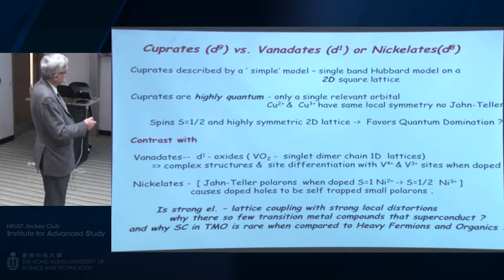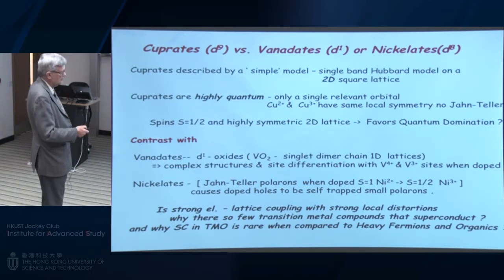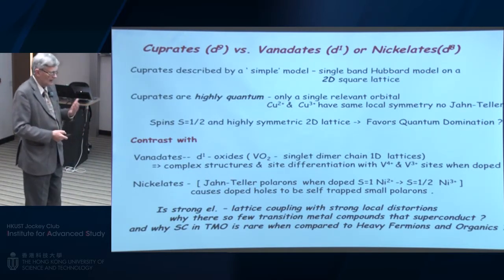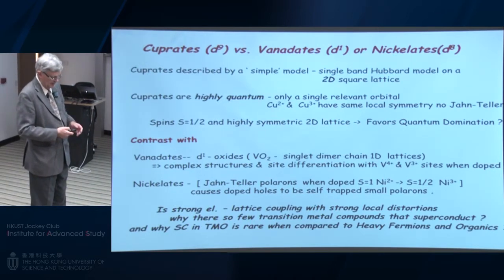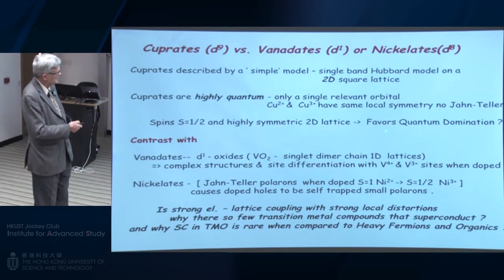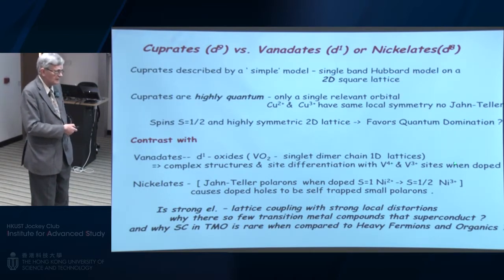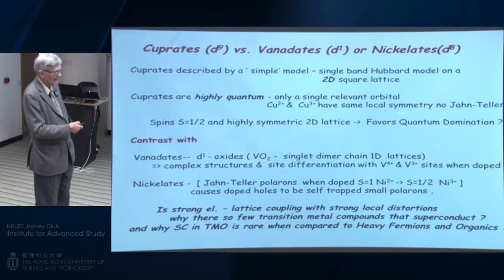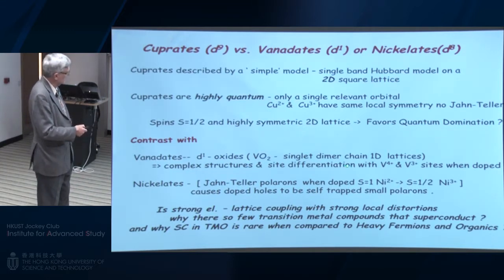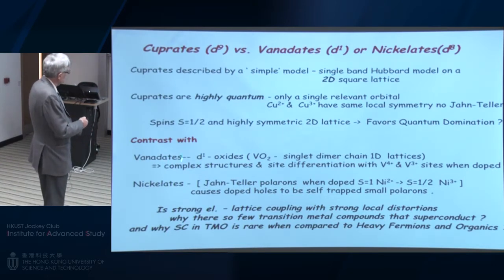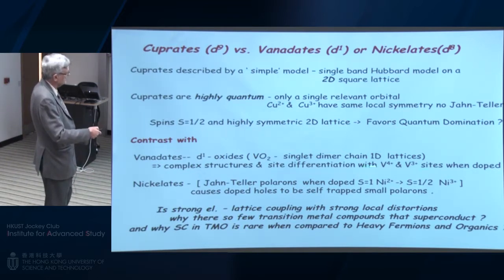And all of these things, you see, favor superconductivity. They favor a quantum mechanical side, and not essentially a classical side associated with coupling to the lattice. And it's this quantum mechanics, of course, which drives superconductivity. There's no classical analog of superconductivity. It's quantum mechanics. And this is then completely different to what we've seen in the vanadates. In the vanadates, we got this singlet dimer chain, complex structure, site differentiation between the 4+ and 3+ when we doped. The nickelates, it's the same. That's one less electron than copper.